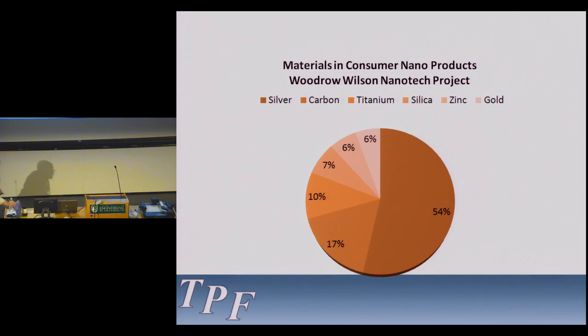And what's quite funny is in order to get around EPA regulations, they all have a phrase like this one here that says, antibacterial technology is designed to protect the pen's surface and does not extend protection to skin. So by doing this, they've been able to get around the EPA regulations, but they're not going to be able to do that for long because EPA is changing that. The real problem with silver is there's about 500 tons of silver now going into everything from toothpaste to socks. And what happens with that silver when it ends up in our septic systems or our sewage treatment systems? It's antibacterial. Well, our systems work with bacteria. That could be a problem.